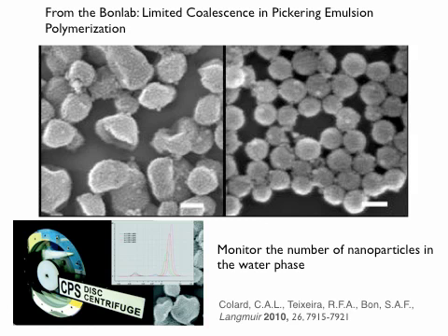So it's very important that you know how many particles are present, and for that, disc centrifugation is perfect, because disc centrifugation is very good at separating particles of different size. So what we did was just made a calibration curve of small particles only, so we can calculate the concentration in the water phase, and you basically follow that as a function of time.